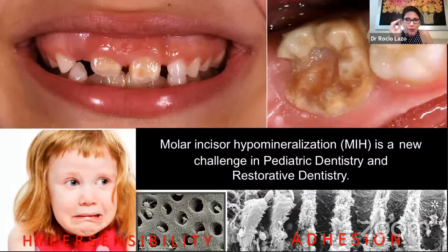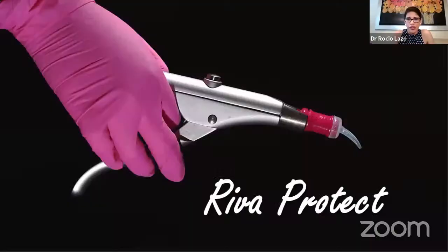Remember that molar incisor hypomineralization is the same, no? It happens in affected dentin. We don't have good amounts of calcium in this tissue, in this enamel. So we need to add calcium. But in this case, we are not going to add calcium. We are going to add strontium. So if you want to do a restoration in a hypomineralized tissue, in molar incisor hypomineralization, use a glass ionomer with strontium to have good results. A glass ionomer of the new generation.